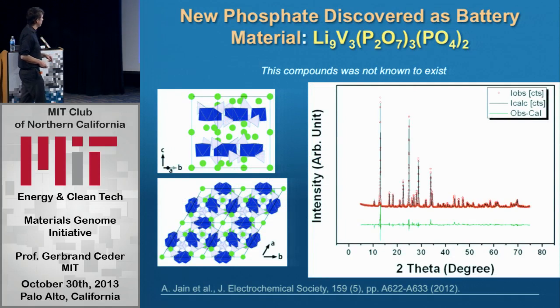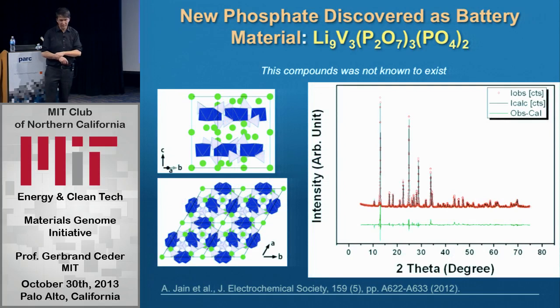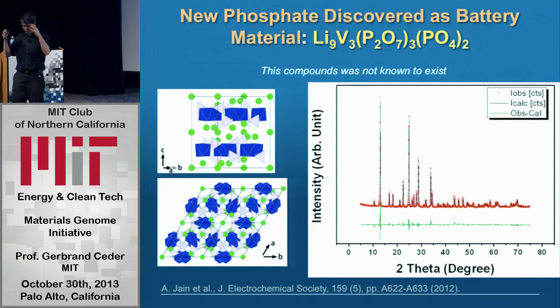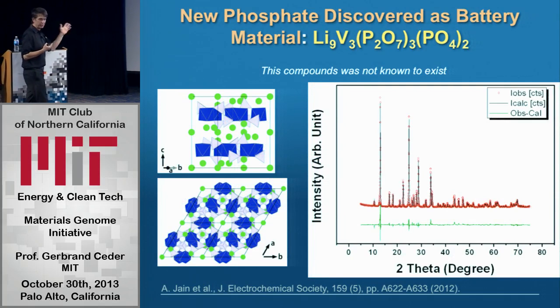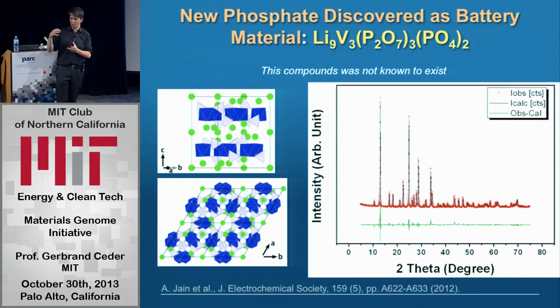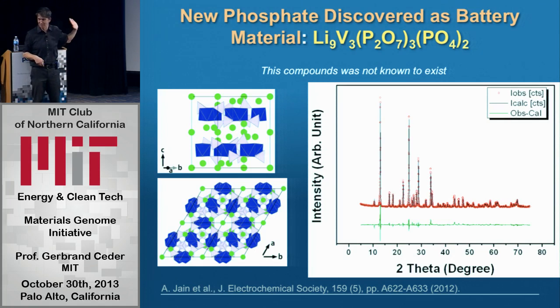And so to make a long story short, we did that on battery compounds. We started off with the idea we need phosphate groups for safety because phosphate locks up the oxygen. And we wanted vanadium, because vanadium is what's called a double redox couple. It has 2 electrons it can exchange, so you can get more battery capacity. So we basically told the computer, take all known compounds and see which ones you can easily make into phosphate compounds or vanadium compounds, or actually both. And it came up with this compound.